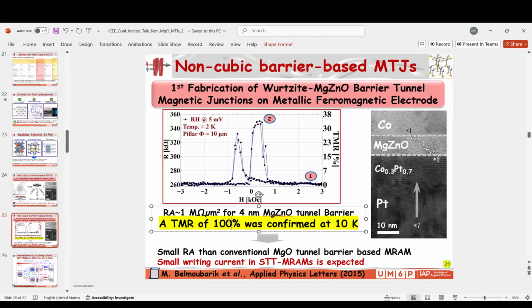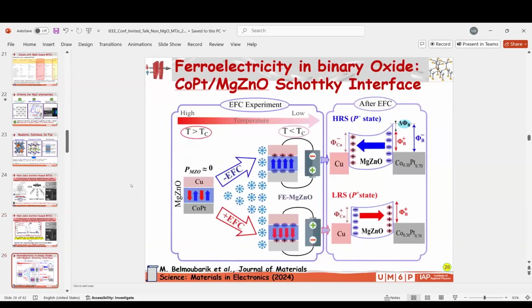So if you include 100% in the Julliere model, plus the spin polarization of cobalt around 30–40%, you will reach some high level, which means we are at the age of spin filtering with the wurtzite magnesium zinc oxide. There are some theoretical calculations, I think done by Professor Imamura of AIST, but he used a cubic one. So this is also a chance for people who are doing DFT to try this material in DFT.